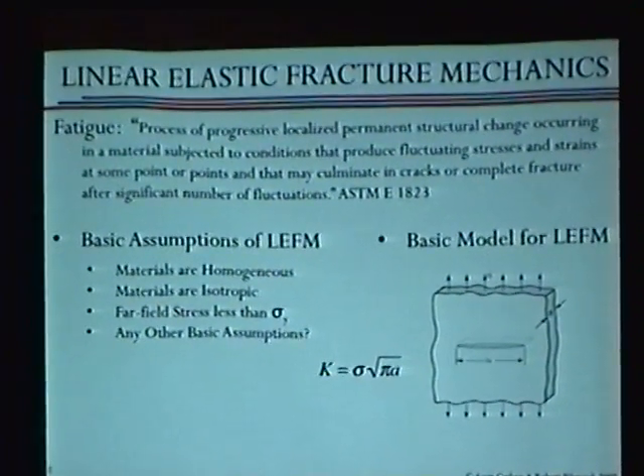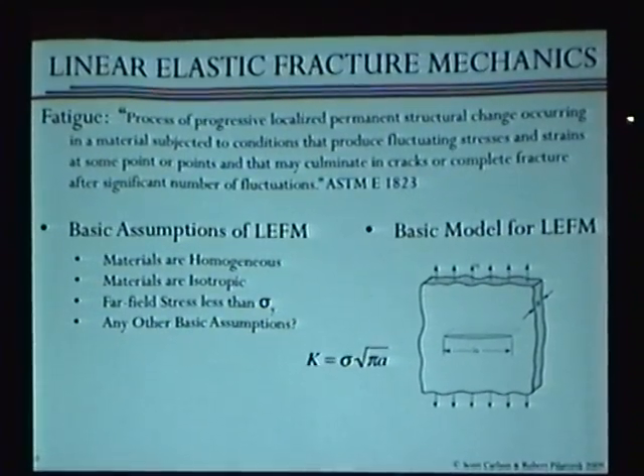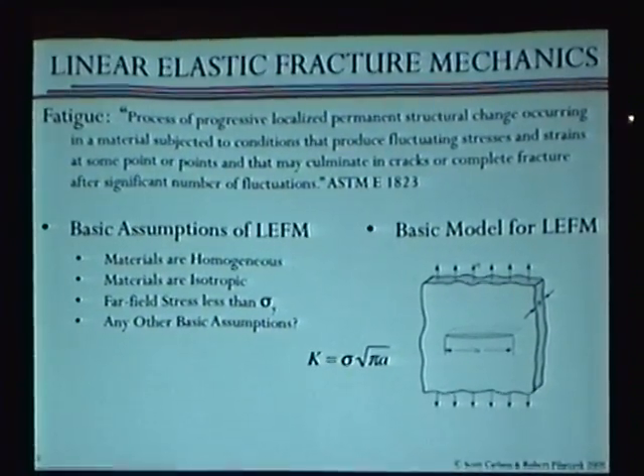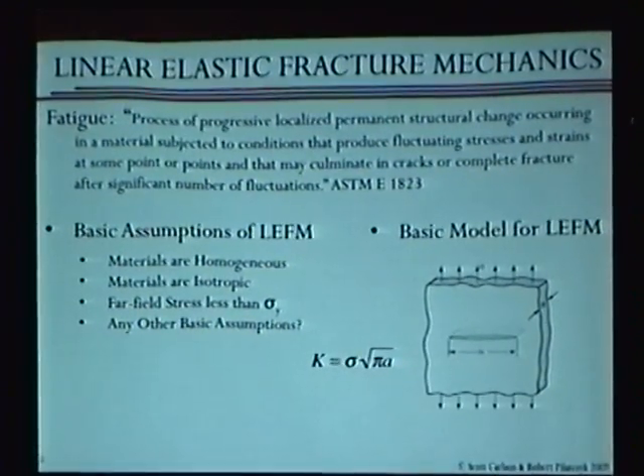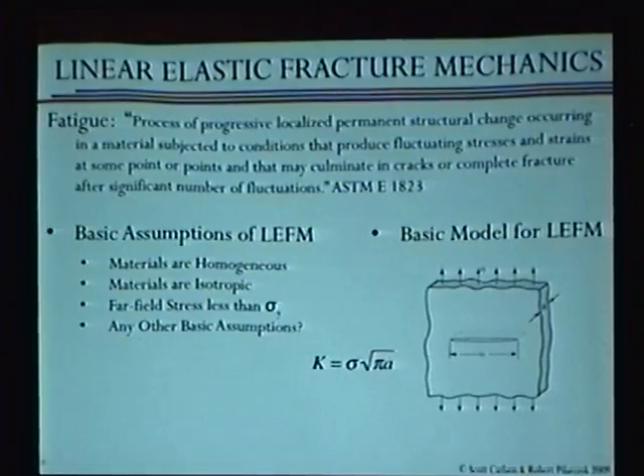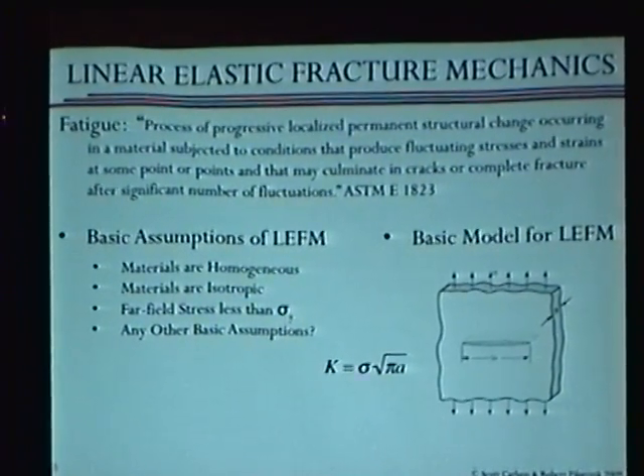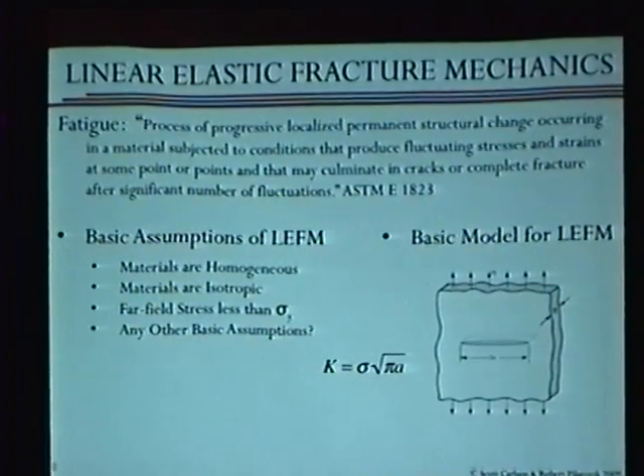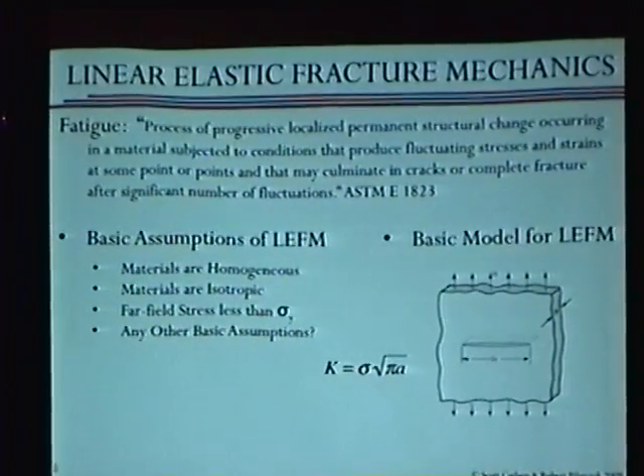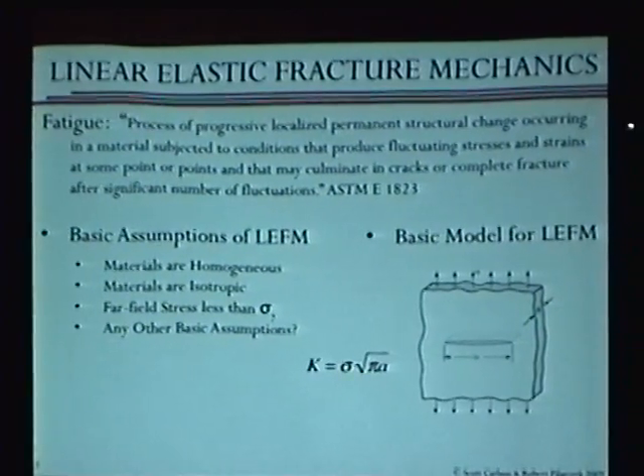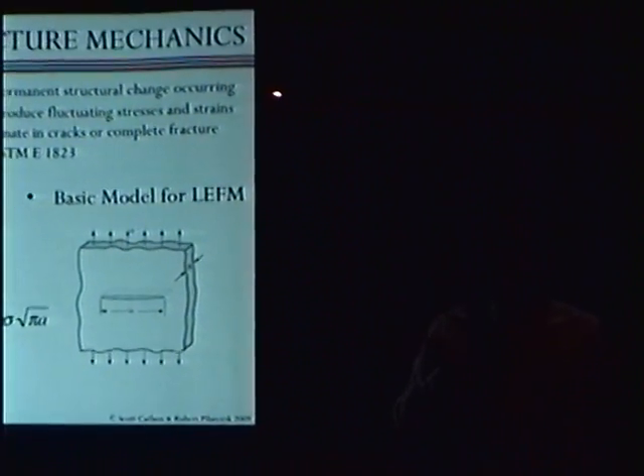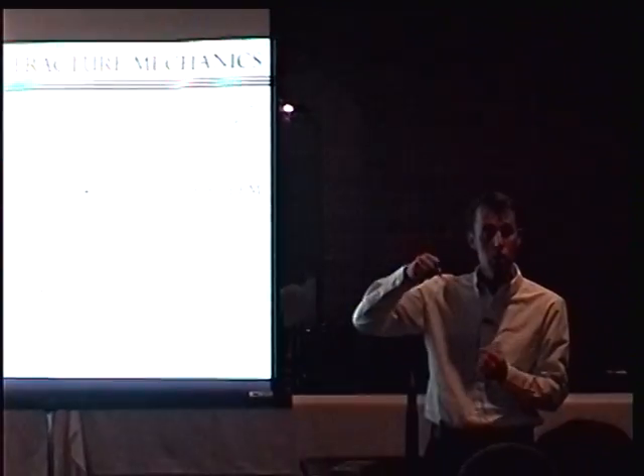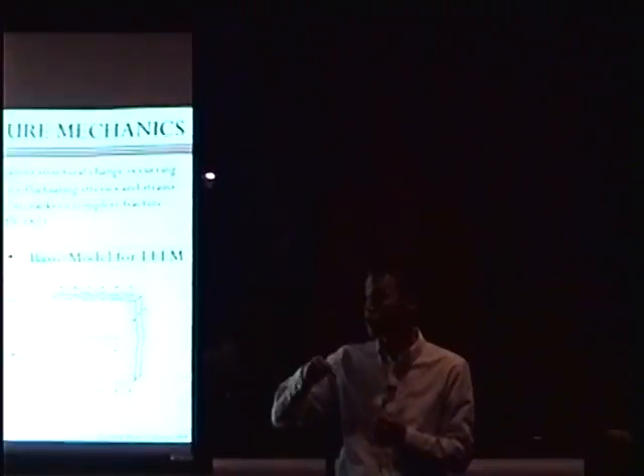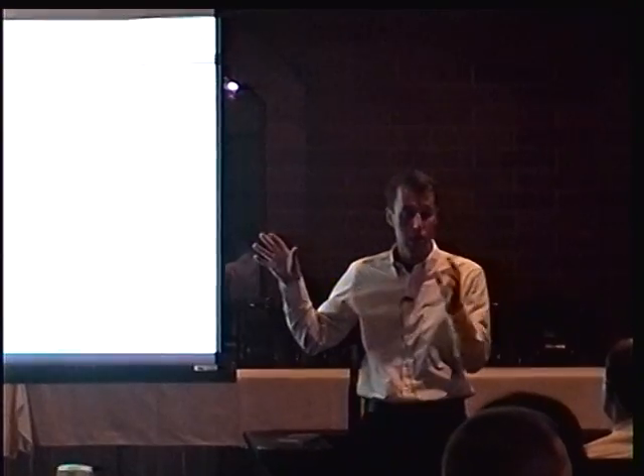It's a process of progressive, localized damage in some structure that occurs because of fluctuating stresses or strains, and can result in either cracks nucleating and propagating, and can culminate in complete failure of the part. So it's important that we understand, one, that it's a process. It's not instantaneous. It's localized and progressive, and it's due to fluctuating strains and stresses. So something is being cycled, and we nucleate something locally, and we propagate it under these local strains and stresses. Okay?